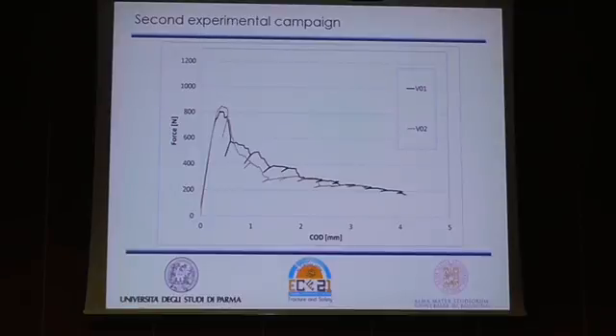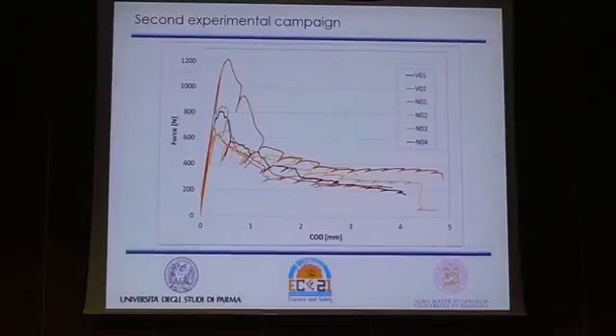The force is plotted as a function of the crack opening displacement. These are the curves relative to the virgin specimens, and these are the ones relative to the nanomodified specimens. We can already see how the N01 specimen dissipates an amount of energy lower than the virgin one. The N04 specimen dissipated an amount of energy higher than the virgin ones, while the N02 and N03 specimens present a first peak, a first critical value of G, lower than the virgin one, but then it increases as the test proceeded.